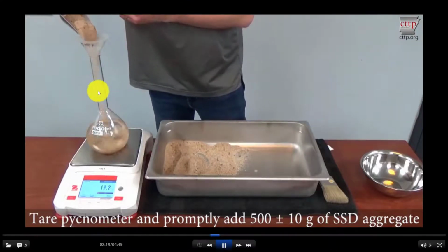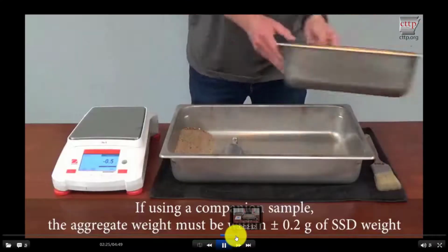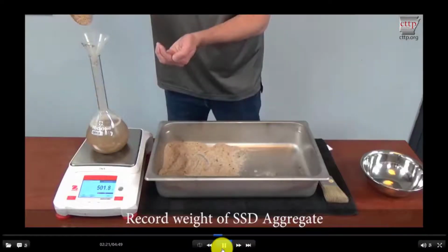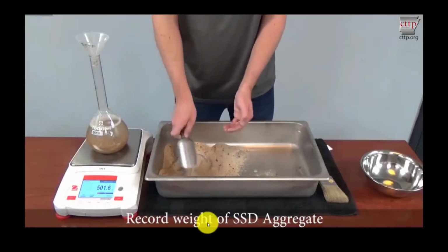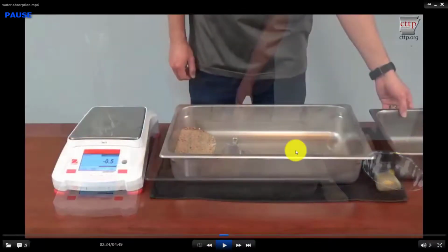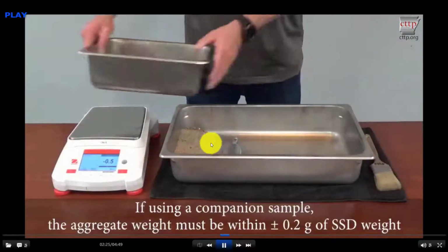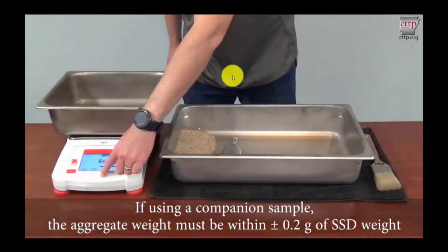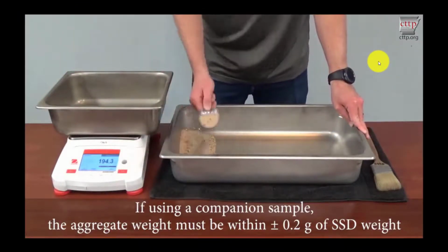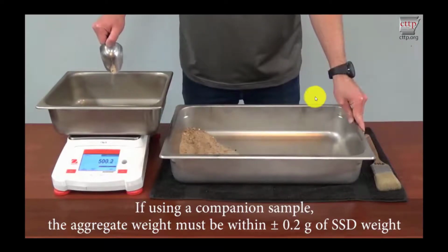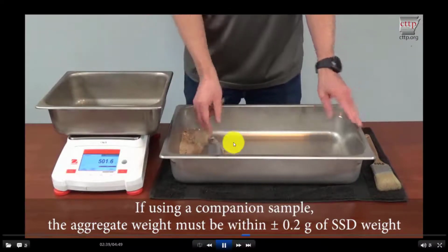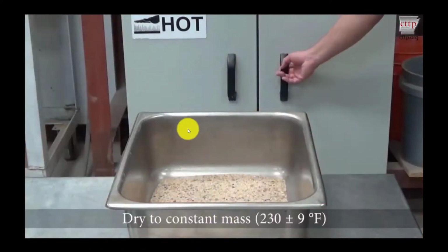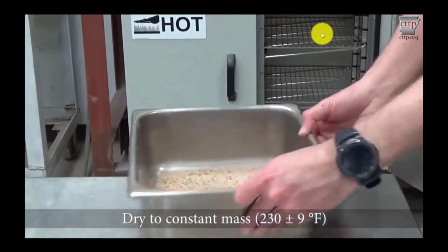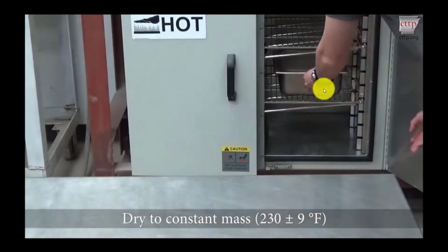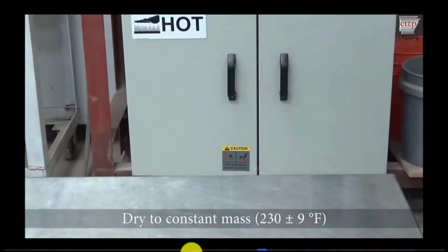500 grams of SSD weight into the pycnometer. After adding the 500 grams of fine aggregate into the pycnometer, you will take the SSD weight of a specimen and keep it for water absorption in the oven for 24 hours at 110 degrees Celsius, so that you can get the water absorption of this SSD fine aggregate. After 24 hours, you will get the water absorption.